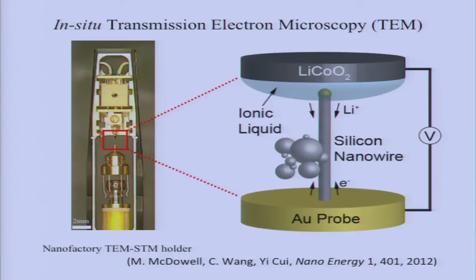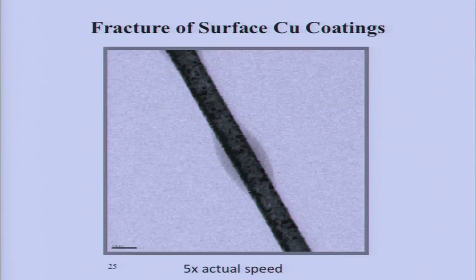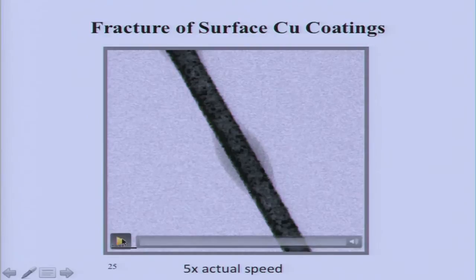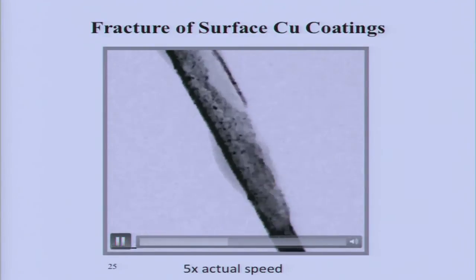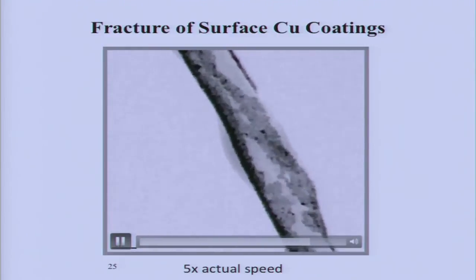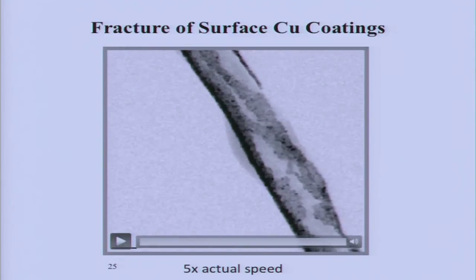Let me share with you some of this video. This is one of them. This is a silicon nanowire coated by copper, about 200 nanometers in diameter. This is the scale bar. Now you see what's happening: you start to drive electrons and lithium will go in, inserting into the crystal structure. This whole nanowire is not broken. They survive. But what's broken is the copper coating on the surface.